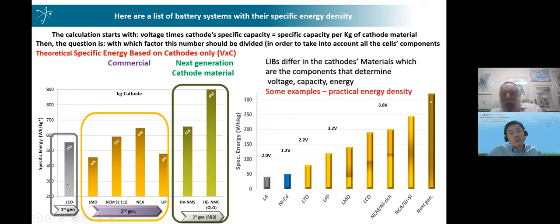So the way we start our calculation, to start our understanding, we take the cathode. Here, this is on the left side. I mentioned several cathodes, and I mentioned energy. We start the calculation by calculating the voltage times the capacity, and then we obtain a number in watt hour. It can be watt hour per kilogram.